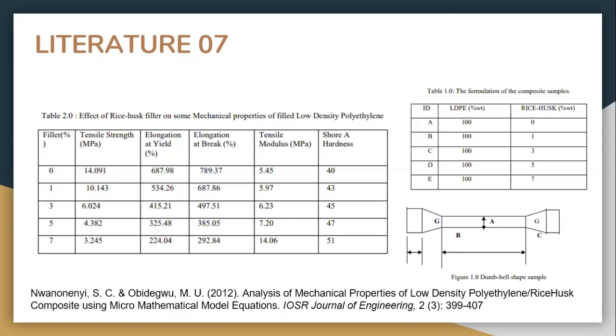On the other hand, the tensile modulus of the sample at 0% weight fraction is 5.45 megapascals and increased to 5.97 megapascals upon the addition of 1% weight fraction. This then gradually increased upon further addition of the filler. Likewise, at 0% weight fraction, the hardness of the sample was only about 40, but increased to 43 upon the addition of the 1% weight fraction. It also increased furthermore upon higher percent weight addition of the filler.